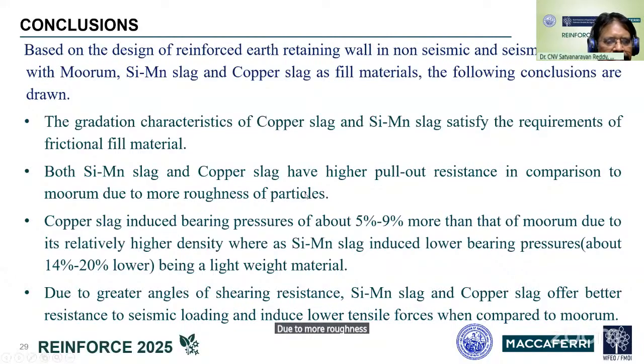So both the slag materials have higher pullout resistance in comparison to moorum due to more roughness of the particle surfaces. And the copper slag induced bearing pressures of about 5 to 9% more compared to moorum due to its relatively higher density, whereas silicomanganese slag induced lower bearing pressures by about 14 to 20% as it is lightweight material. Due to greater angles of shearing resistance, the slags offered better resistance to seismic loading and induced lower tensile forces when compared to moorum.